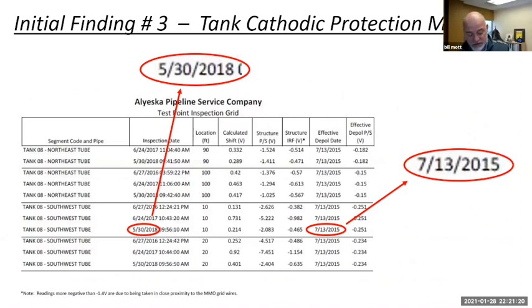There are several issues. First, this is the deep hole data. It was collected in 2015. The standard requires that you use the formation or the decay of polarization to determine whether you have 100 millivolts of shift. And typically what they do is they measure the deep hole, they subtract it from the instant off reading, and that gives them this number. In this case, 332, that should be great. But this was collected in 2015. This one was collected in 2017. The instant off data was collected 1, 2, and 3 years later.